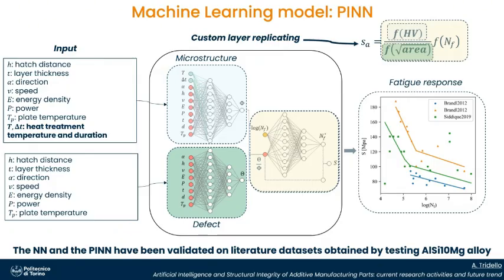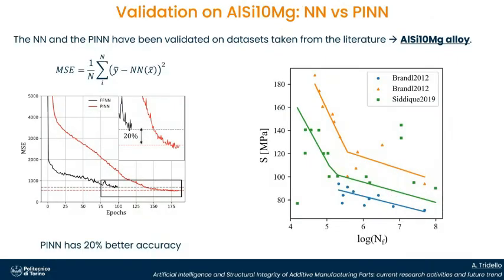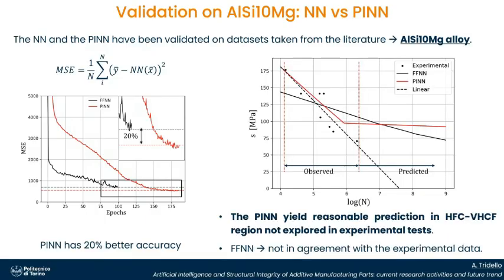So this physics-informed neural network has been validated on a literature dataset obtained by testing the aluminum silicon 10 magnesium alloy. Okay, we take this data from the literature and we consider a powder bed laser beam process. Okay. And you can see this one is the loss function for the mean square error, the black one for the black box approach, and this one is for the physics-informed neural network. We obtain a better accuracy by embedding physical knowledge. And you can see this is a result of the validation we have made. And this has been obtained by considering the physics-informed neural network.